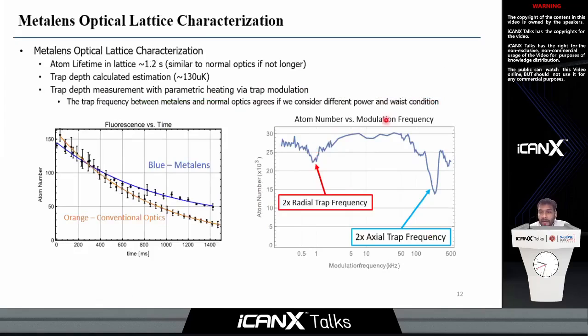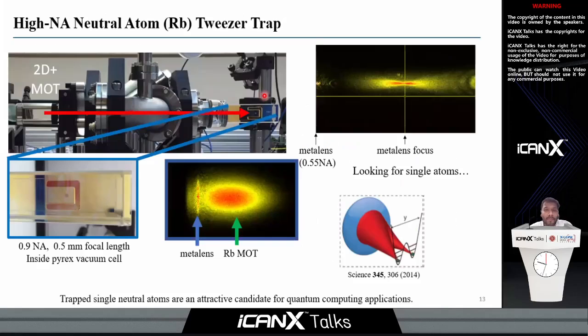One can now look at these trapped atoms quite carefully, their lifetimes, or look at the atom number as a function of modulation frequencies and compare them to conventional optics. And basically what this slide is showing is that metalenses are really not doing anything untoward to the atoms, and they are basically behaving very similar to how one would expect a conventional optical element to behave. So this was quite promising, and where this is really going is trying to use metasurfaces to trap single neutral atoms, and these single neutral atoms act as qubits and are a very attractive candidate for quantum computing applications.